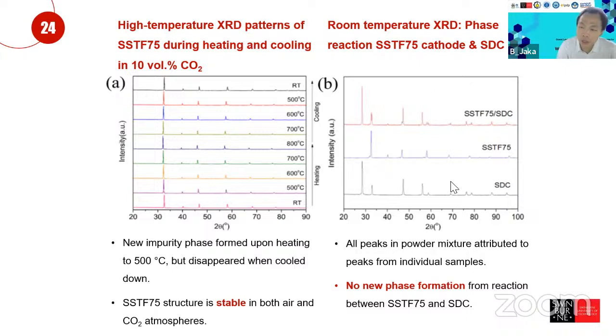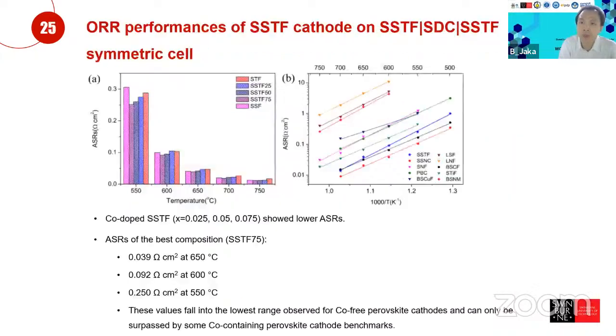Okay, and then we do what we did in the previous slides as well. We basically check, after we sinter this SSTF 75 with the SDC, whether they are stable, whether there is no evidence of phase impurities forming in the system. And yeah, we did get a good result, which means that we don't find any peak impurities that come out after we mix up the two powders, the electrolyte with the cathode, and we heat it up to high temperature.